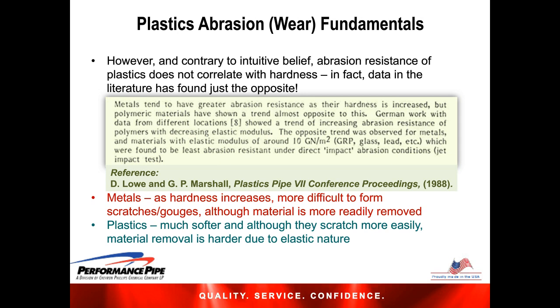The point basically then is that the difference is thought to be due to the fact that in metals, which are much harder, as the hardness increases, it's more difficult to form a scratch or a gouge. But once a scratch or a gouge has formed, it's easier to remove the material. Plastics, on the other hand, are much softer, and although they may scratch more easily, the material removal is harder due to the elastic nature of the material. In other words, the viscoelastic nature of polymers affects the abrasion resistance characteristics more so than simply hardness, as is the case with metals.